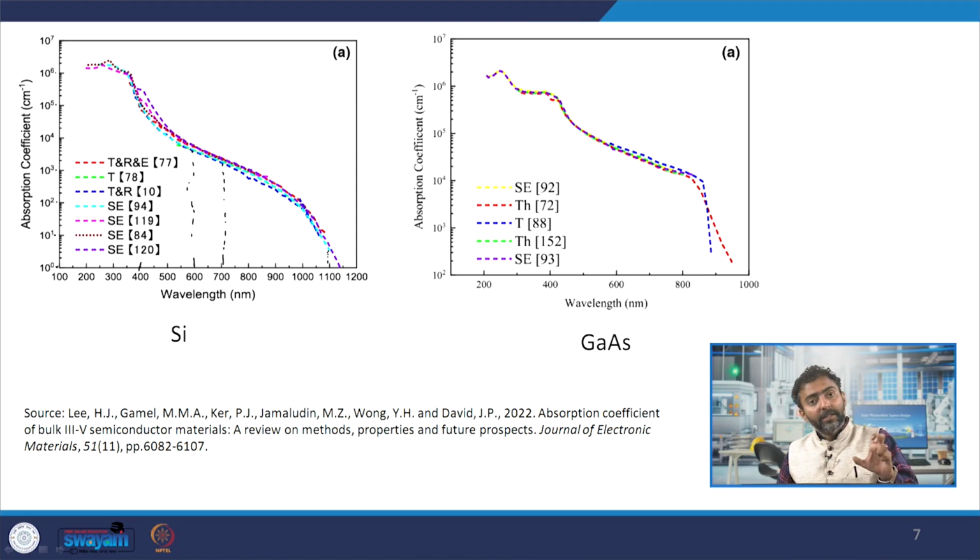Whereas the low energy radiation, which is the infrared radiation, is not easily absorbed; it has a low absorption coefficient and is absorbed much deeper in the solar cell. So, the smaller the wavelength, the earlier it is absorbed in the solar cell. The top layers of the solar cell will absorb any ultraviolet, violet or blue end of the spectrum, whereas as you go deeper and deeper, the red end of the spectrum or the infrared will be absorbed only much deeper in the solar cell. So, that is a common phenomenon.